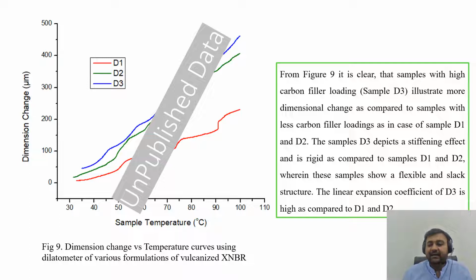We changed the temperature from 30 to 100 degrees Celsius, and from the figure it is clear that with high carbon filler loading there is more dimensional change as compared to the samples with less carbon filler loadings, as in the case of samples D1 and D2. The sample D3 depicts a stiffening effect and is rigid as compared to D1 and D2, whereas the samples which are flexible and have a slack structure show less dimensional change. The linear expansion coefficient of the rubber with the highest hardness is high as compared to the samples with the lowest hardness.